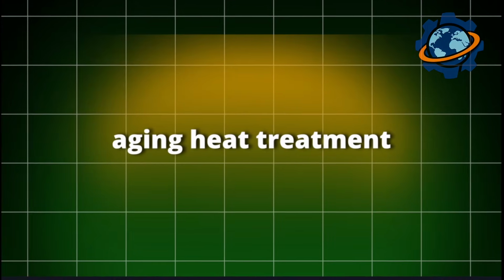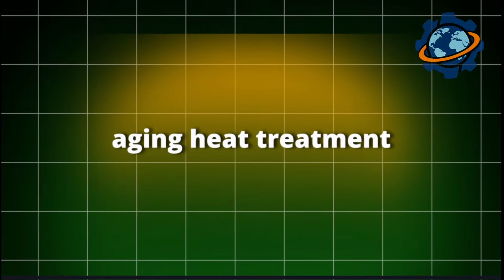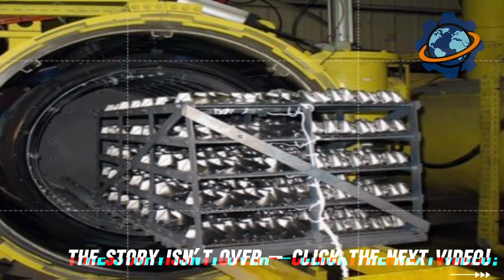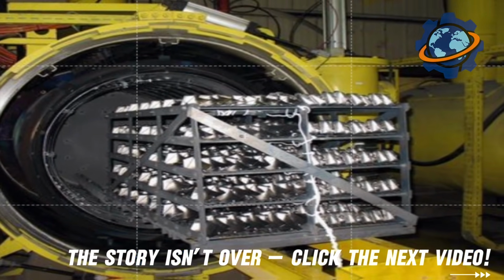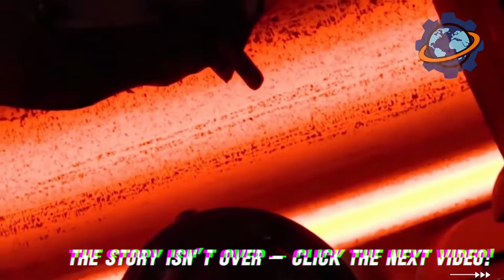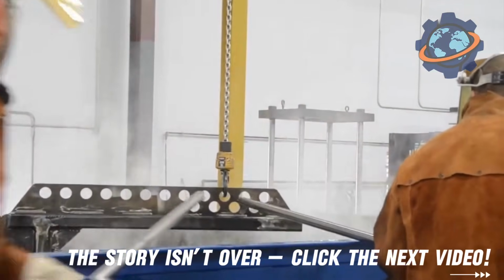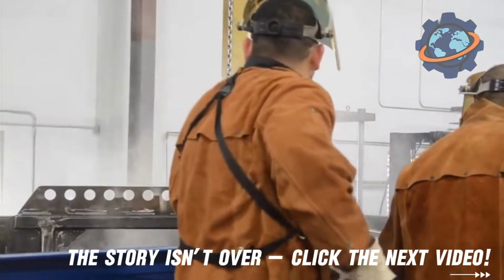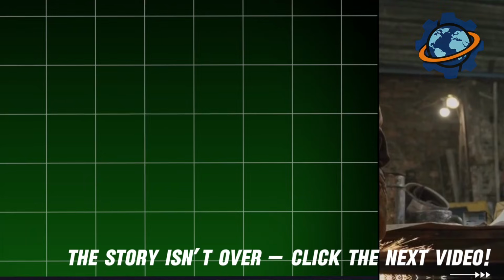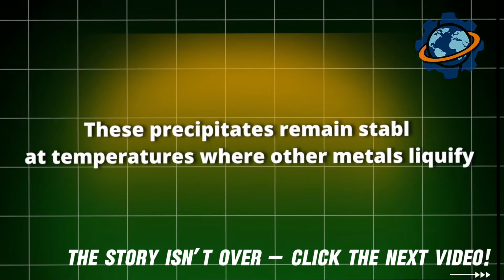Next comes aging heat treatment, multiple cycles at precisely controlled temperatures that cause nanoscale particles to form. These particles, called gamma-prime precipitates, occupy 70% of the alloy's volume. Picture this. Imagine a three-dimensional checkerboard where hard particles pin the crystal lattice, preventing atoms from sliding. These precipitates remain stable at temperatures where other metals liquefy.